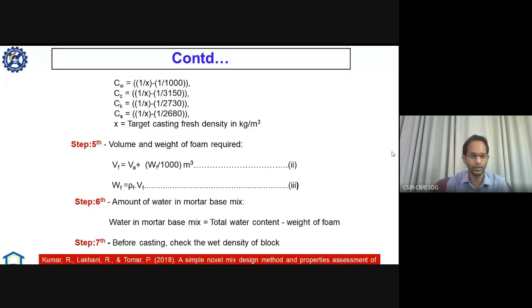Then we have found the volume of air, and then weight. And then we have determined the amount of water in the mortar-based mix. What does mortar-based mix mean? Mortar-based mix is just the mortar mix without foam. So we have subtracted the weight of foam, because the overall water cement ratio should be constant. Otherwise, it will affect the workability of the CFC mix. And if the CFC mix is not stable, then segregation of the green cellular foamed concrete mix will occur, like as we know in case of normal concrete.